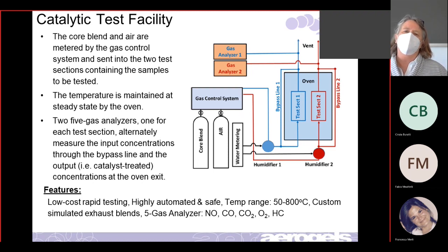And then the oven here is used to set the temperature. So we run temperature sweeps. We could start at 50, but we usually start at about 100 degrees C. And then we go to 150, 200, 250. We go through each set of temperatures, and we measure for each one what the conversion is.